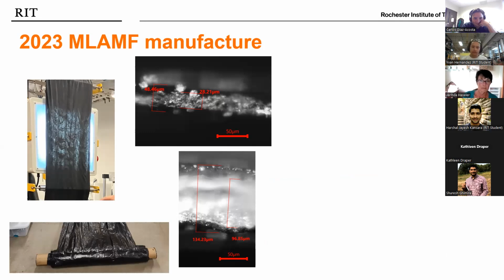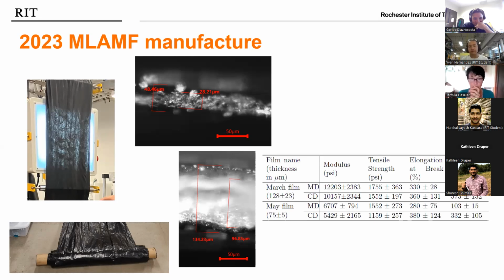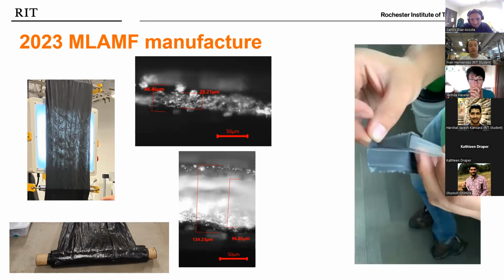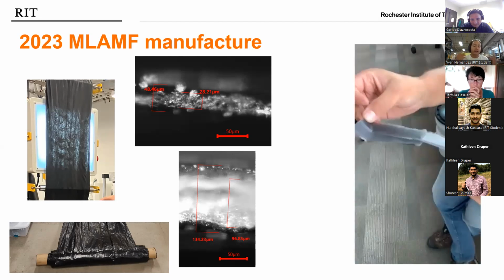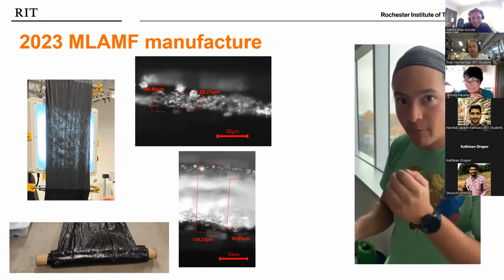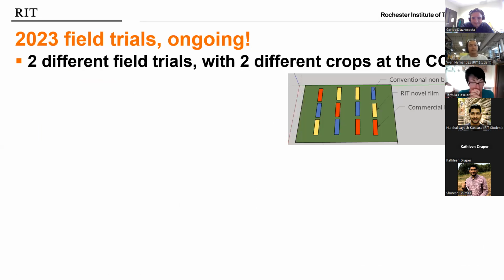However, because here in the lab, this is not an industrial manufacturing facility, I cannot have the homogeneity that I would like to have 200 or 400 feet of exactly the same thickness. So mine range between 150 and 50 micrometers, which was good enough for our field trials. And our tear resistance was where we wanted it to be, and our tensile strength also. So it was even able to delaminate, and we could even eat that starch layer because starch is dissolvable and we can actually eat it. So then we went ahead and tried it in the field. 2 different field trials with 2 different crops. One was onions, one was watermelons, in a full randomized block design.